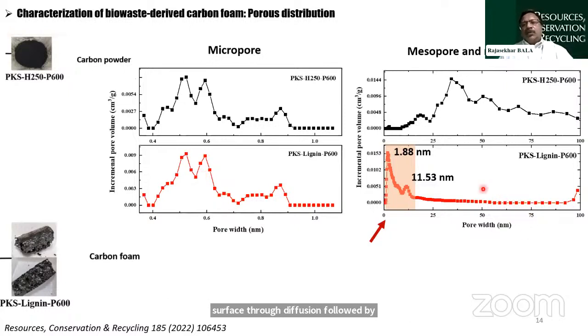At the same time, we also have a little bit higher pores. We call them mesopores and macropores, which would be complementary to the role played by micropores. In other words, if we have a multi-porous structure carbon foam, it will turn out to be more effective in removing carbon dioxide than just a monoporous kind of carbon structure, carbon foam.